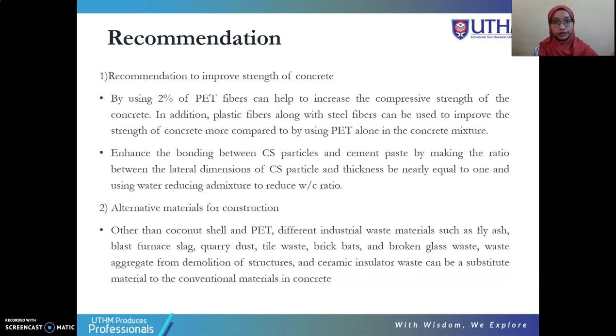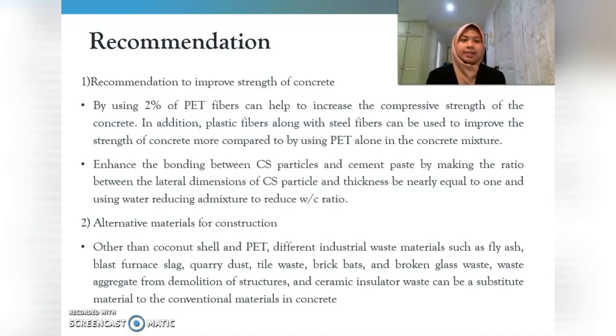Next, we also can improve the strength of concrete by enhancing the bonding between coconut shell particles and cement paste. To enhance the bonding, we must make the ratio between the lateral dimension of coconut shell particles and the thickness of coconut shells nearly equal to 1, and use a water-reducing admixture to reduce the water-to-cement ratio. Other than coconut shell and PET, we also can use fly ash, blast furnace slag and quarry dust as aggregate substitutes in the concrete mixture.